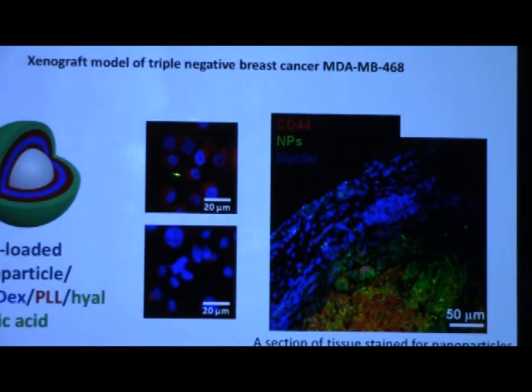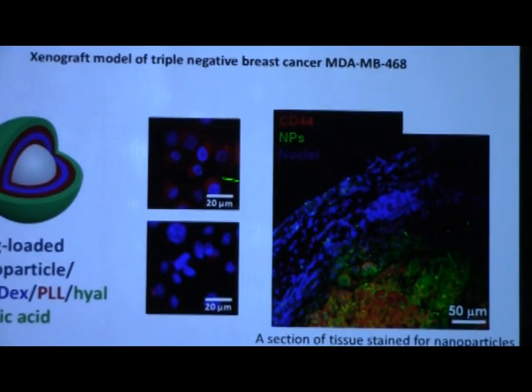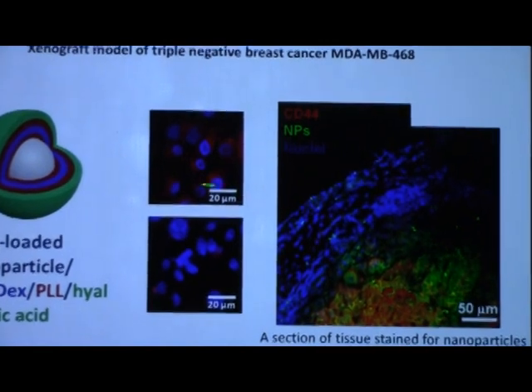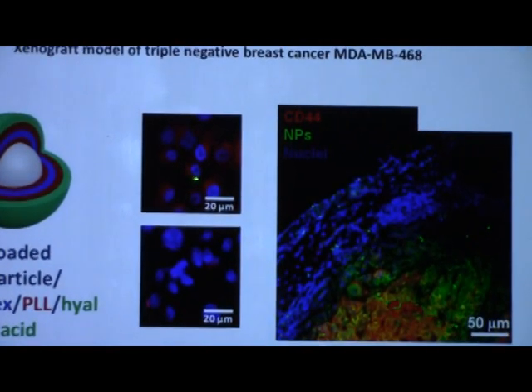So here you can see, hopefully a little bit better, that the nanoparticle is in cells here that overexpress CD44. We've labeled it red. So you can see the nuclei of the cells are blue. And you can see that you don't see the red in the cells underneath. And that's because we essentially titrated that with a large amount of free hyaluronic acid to compete out the nanoparticles. So we can show that this binding is very specific to the presence of hyaluronic acid.